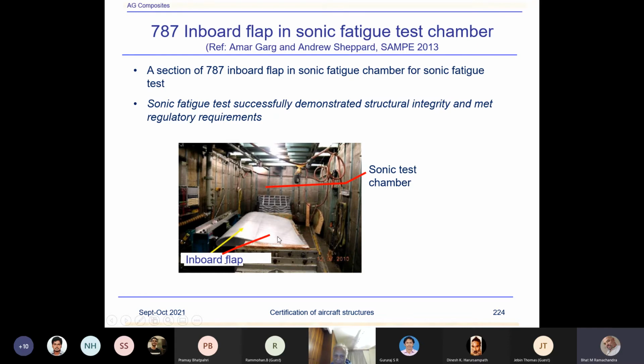Pardon? The sensors on the component are primarily strain gauges over here, just to demonstrate, because the modeling of that particular sound pressure level was done on the structure. Basically, the sonic load is nothing but sound pressure levels, which are pressure distributions. These pressures will create structural deformations, vibrations of some modes, modal vibration, and then there will be strains generated. That is what was noted and shown. So mode shapes were looked into, studied using the finite element method, to match that the mode shapes behave similarly to what the analysis showed on the component, and also the strains on the skins at various places.